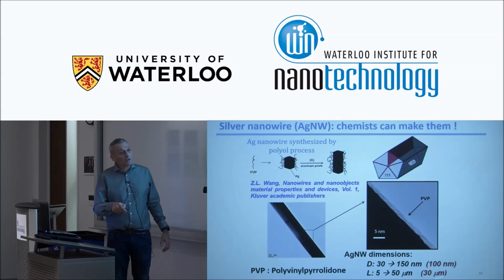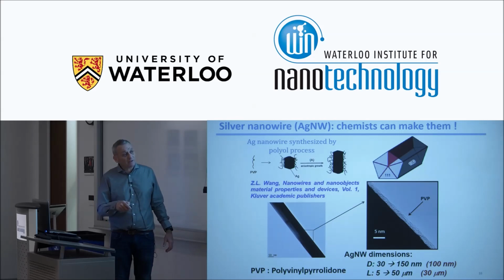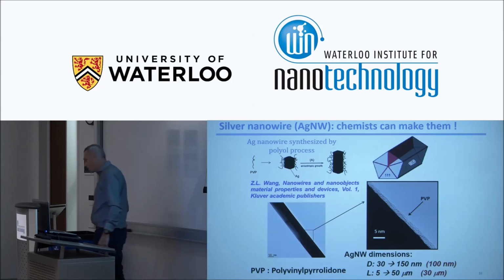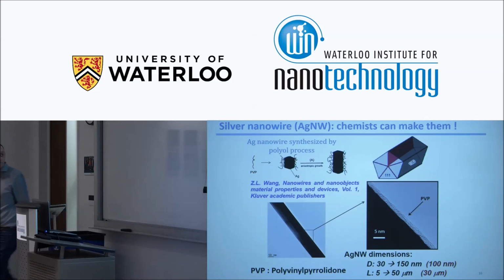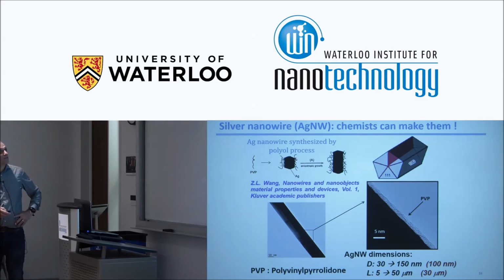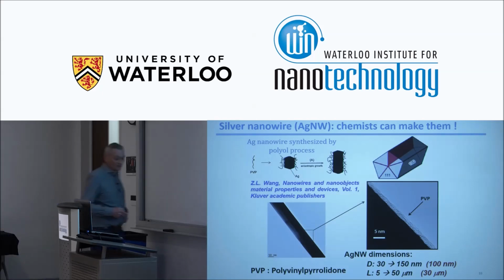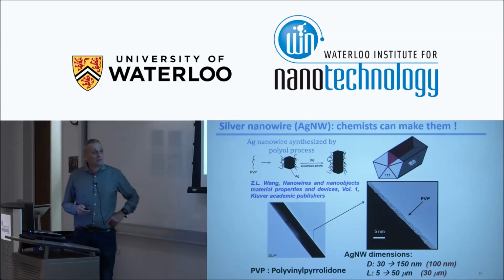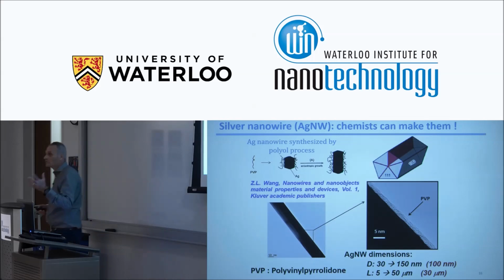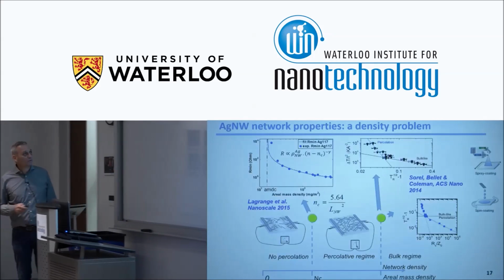And so we can buy commercially, or we can collaborate with chemists to have silver nanowire diameter of, let's say, 100 nanometers, and length about a few tens of microns, or even a few hundreds of microns in some cases. We receive that in solution, and you can deposit these nanowires on a glass substrate, on a polymeric substrate, using either spin coating or spray coating, for example, or Meyer rod, for example.